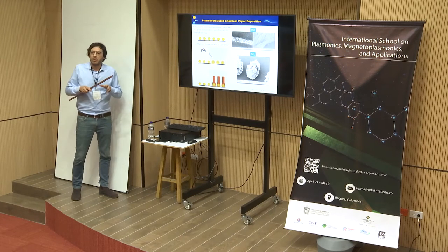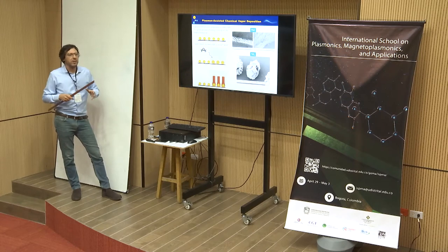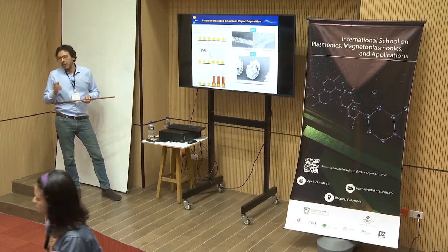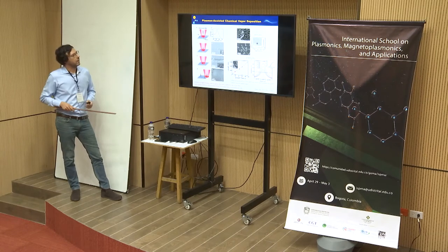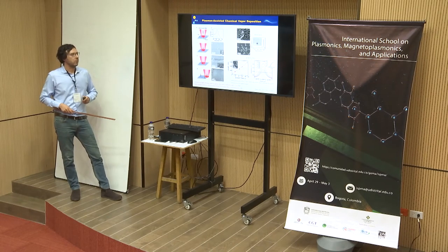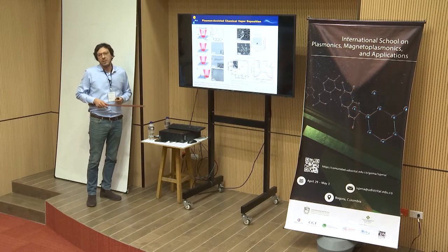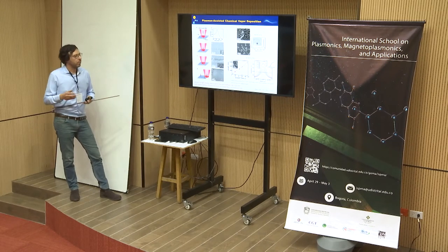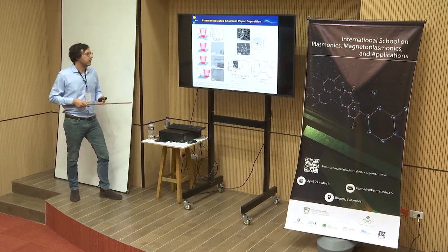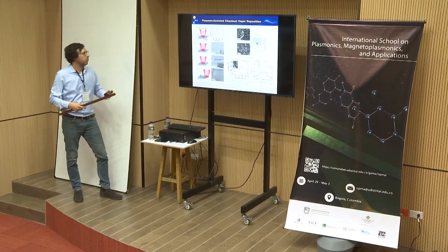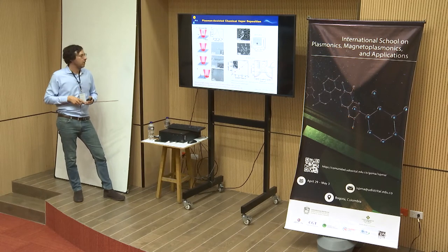So this is very important, for example, for catalysis, if you want to create core-shell nanostructures, or you want to selectively functionalize a specific platform to be used, for example, for biodetection or other purposes. And it's also interesting, this is again another example, they were also able to grow single nanowires templated on the metal particles. In this case, this process is really mimicking what's happening, for example, in normal vapor-liquid-solid processes which are used to grow nanowires. So you heat up the single plasmonic particles, and you put your chemicals inside in gas form, and so you can create a single nanostructure in the precise position that you want.